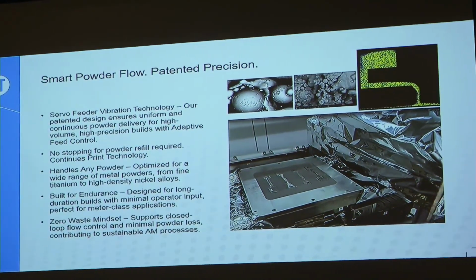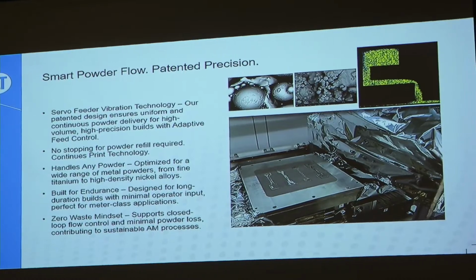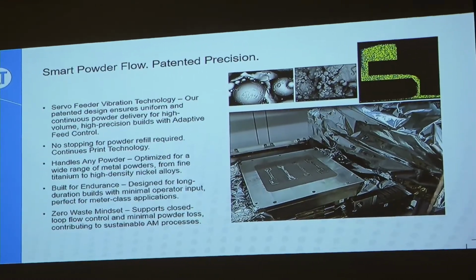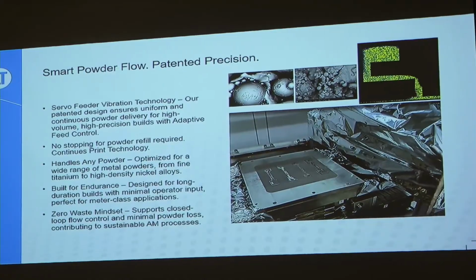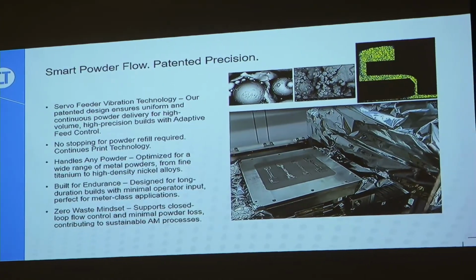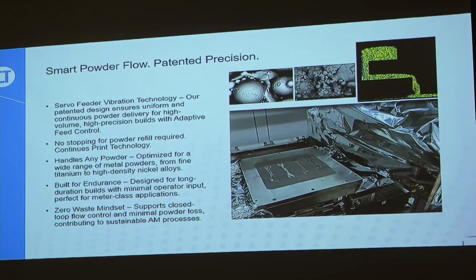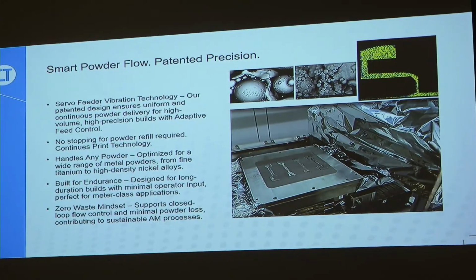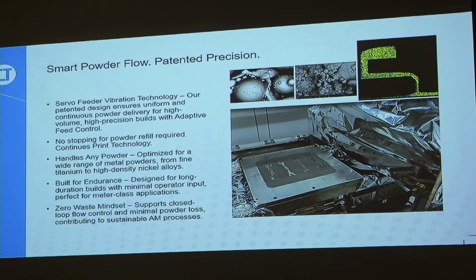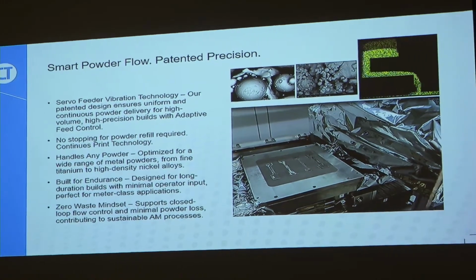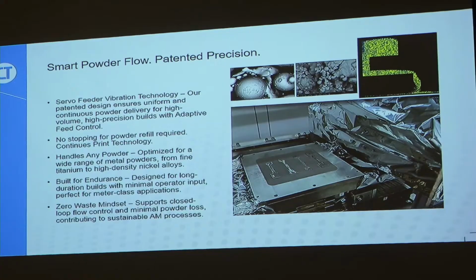The other thing we found is, because we use this vibration system, is that when we have these powders, we create higher densities in the powder bed. Because if you have spherical powders that are very good in flowability, they create a lot of empty space in there. If you have asymmetric powders, when they form them, they can create better densities in the powder bed. But that depends on your powder and the material you want and how the powder was manufactured, right? So that's a science in itself. Powder manufacturing is actually a big scientific group.